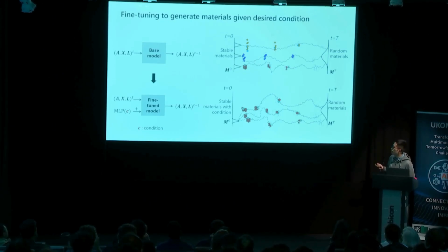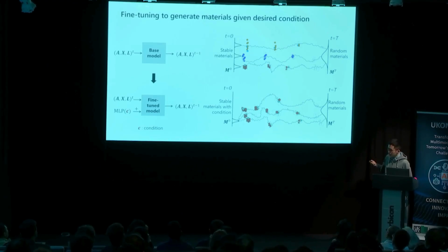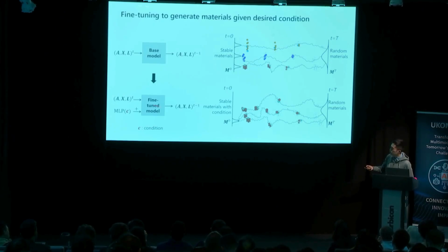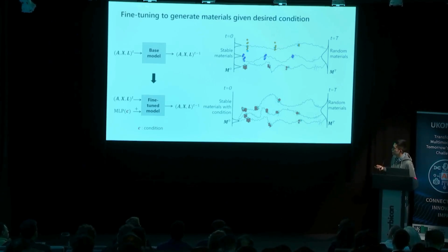So this is enabled by fine-tuning. We take the base model, and what you need is a small labeled data set where you have pairs of structures and their properties. Then you can add the property that you're looking for as a specific condition. We put this into an MLP, and then sum the embeddings you're getting into the node embeddings of the score network. This alters the scores of the score network. Therefore, once you've done the fine-tuning, during generation you will only generate materials that satisfy the properties that you define. And here, we use something called classifier-free guidance, consistent with what people use in text and image generative models.